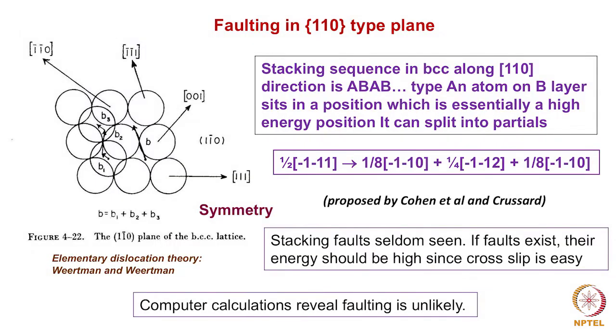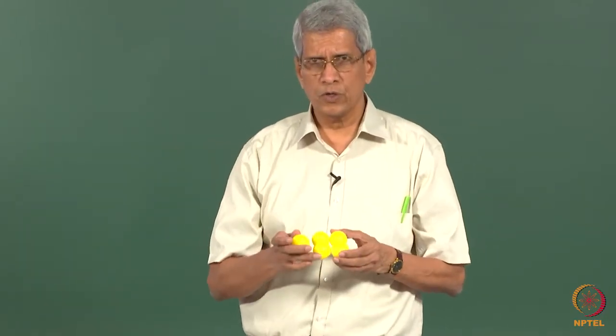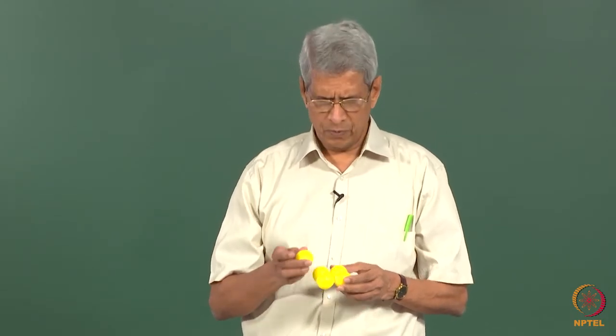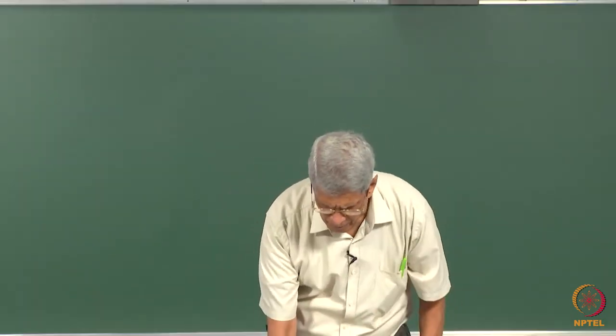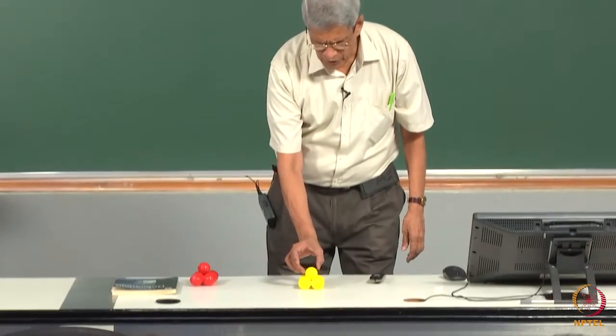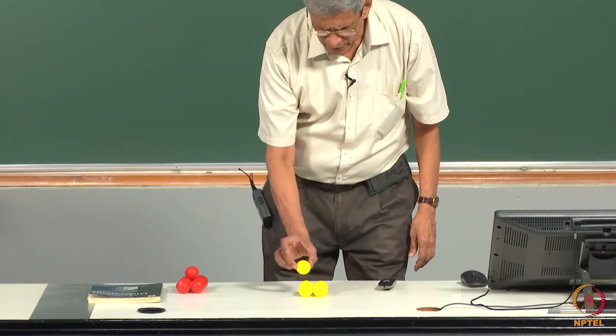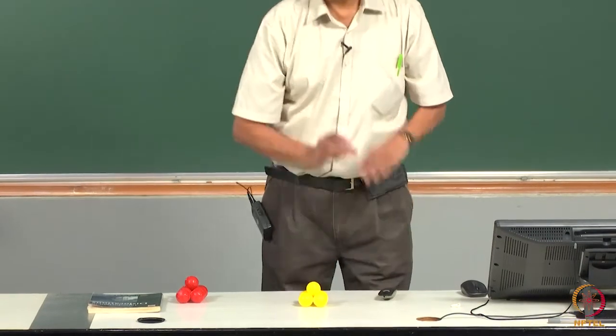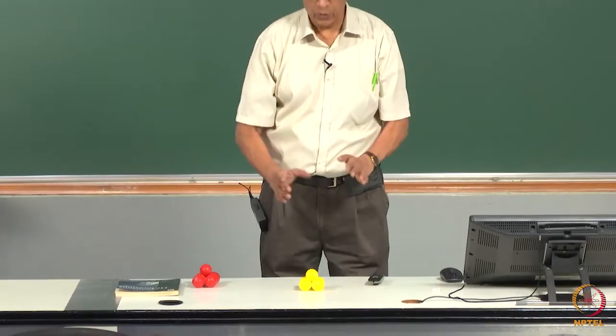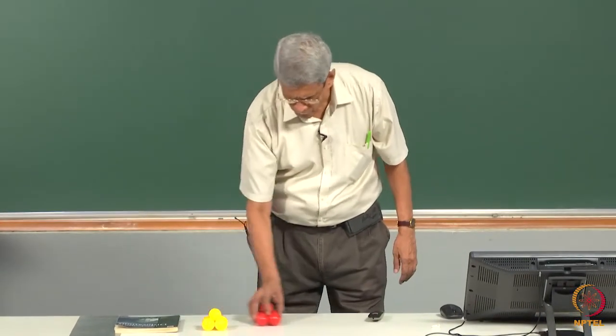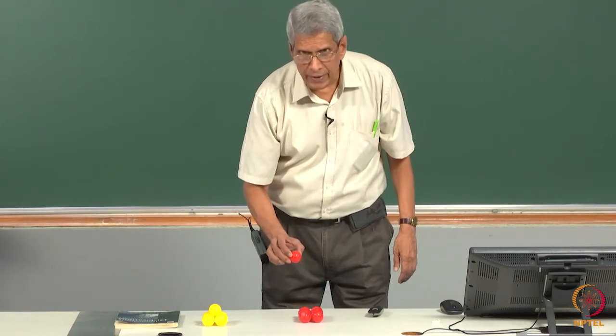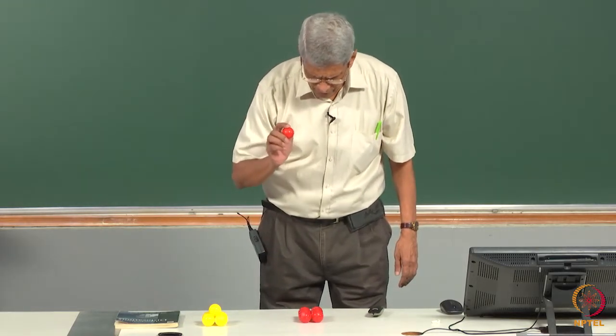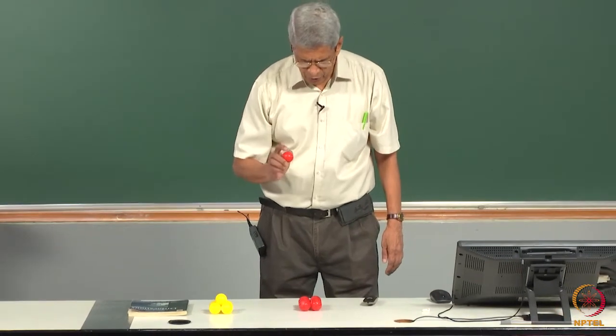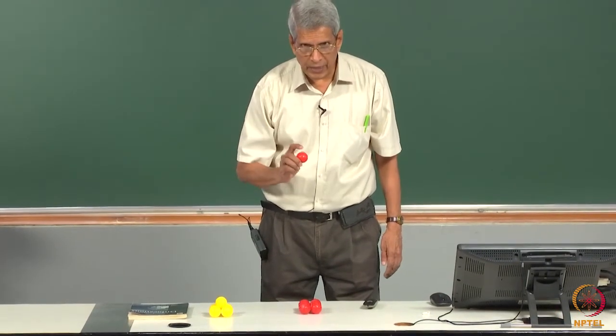Let us just look at the structure of the dislocation in the 110 plane. This is the packing along the 001 plane. If it is an A layer, the B layer will be coming on top of it. So this is at a low symmetry position. It is quite stable. It just doesn't move because we are looking at the hard sphere model. If we look at the 110 plane, here also the stacking is essentially an AB type of stacking.